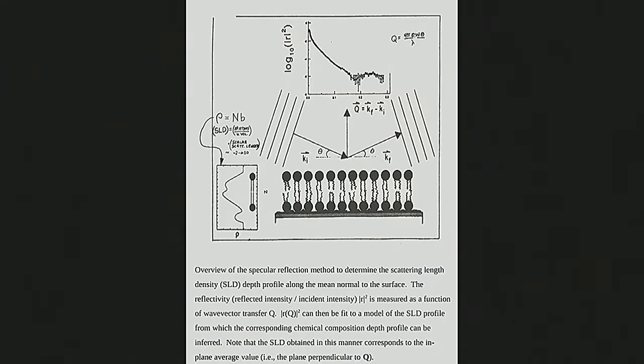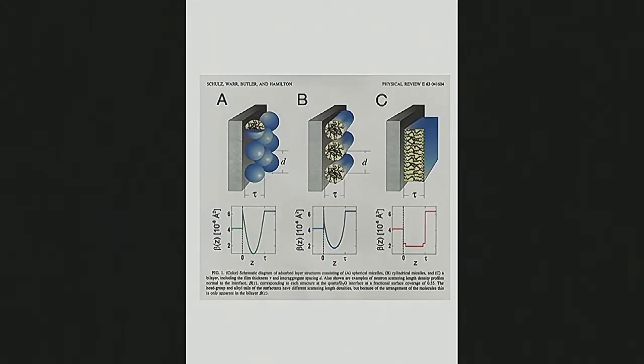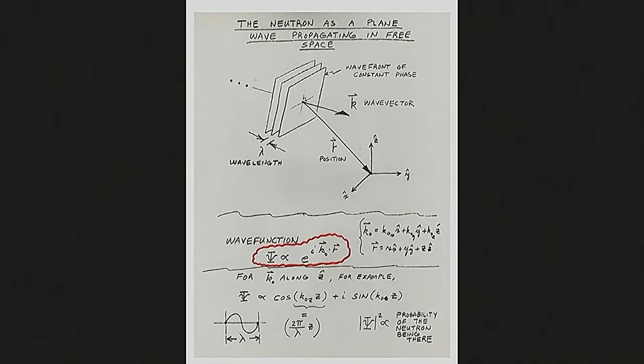Here's a picture showing, for example, if you had spheres lying on the surface, the average profile you'd get is some parabolic shape. If they were cylinders, it would again be parabolic but a little bit broader. And if it was lamellar, you'd get a more rectangular profile.